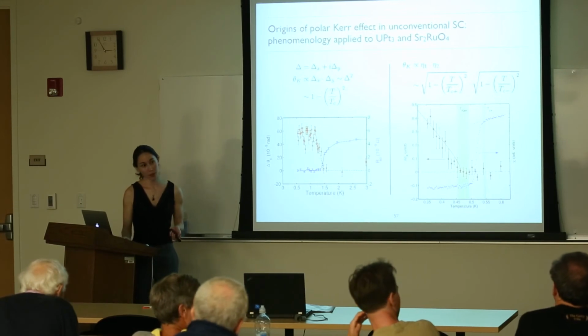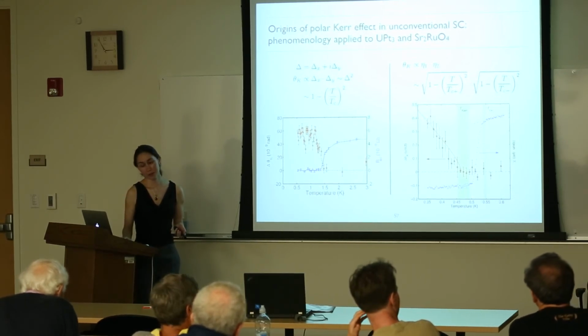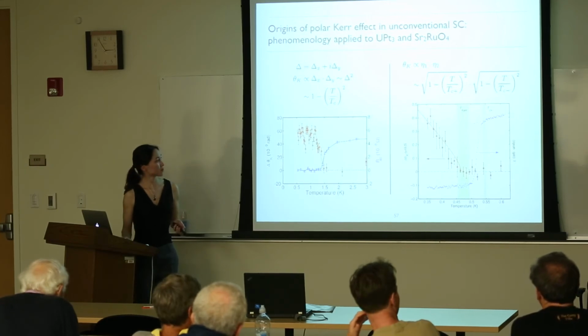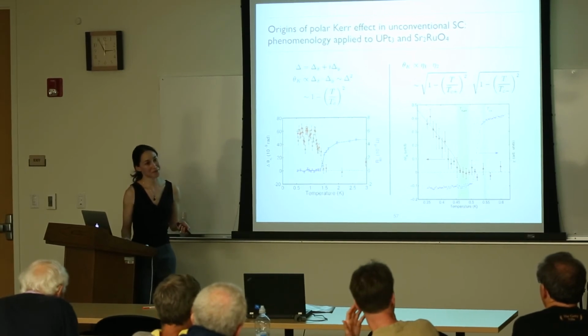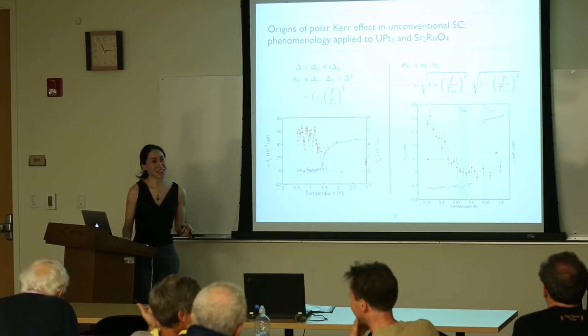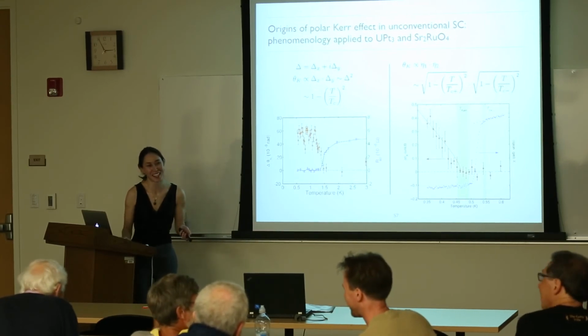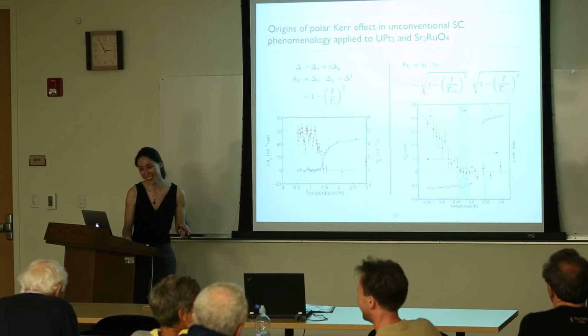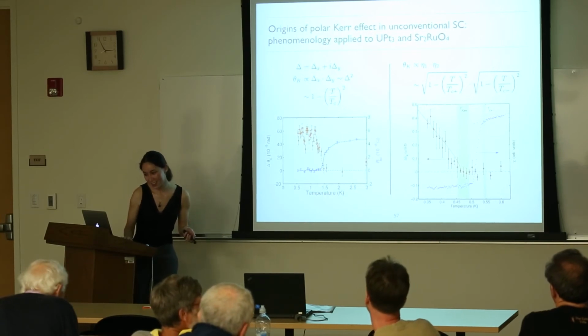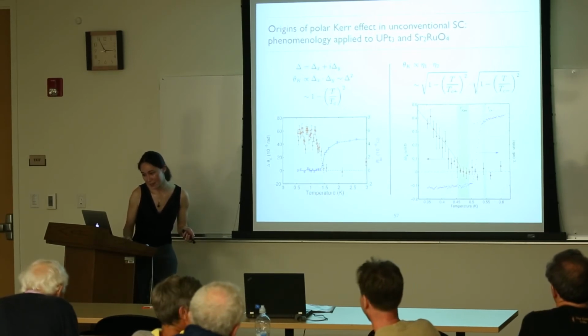You know, this is a completely sensible theoretical expression to fit it to. The thing that the data looks more like is that it rises linearly with T minus Tc below the lower transition temperature. No, I don't disagree. The two Tcs are so close to each other, I don't think you can tell from the error bars.